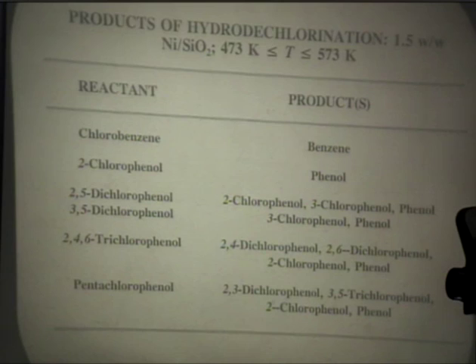This is true of nickel silica operating in the gas phase over these temperatures. We haven't really gone above 300 degrees because we're getting outside truly catalytic phenomena. Palladium catalysts are far more reactive - in the palladium system in both liquid and gas phase, benzene will further undergo reaction to give cyclohexane and phenols will undergo further hydrogenation to give cyclohexanone and cyclohexanol. The really positive feature of the nickel catalysts is the temperature of operation isn't too extreme, and you have 100% selectivity in terms of hydrodechlorination with no ring hydrogenation and no hydroxyl group hydrogenolysis.